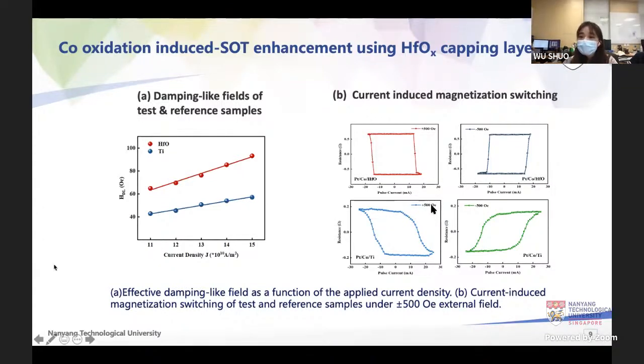Then we investigated how the enhanced SOT efficiency affects the current-induced magnetization switching. You can see in this figure, for our HfOx capping sample, the critical switching current is reduced by about 20% compared with the reference sample. We think the smaller switching current is mainly due to the higher damping-like torque efficiency, which is good for low energy cost devices for further applications.